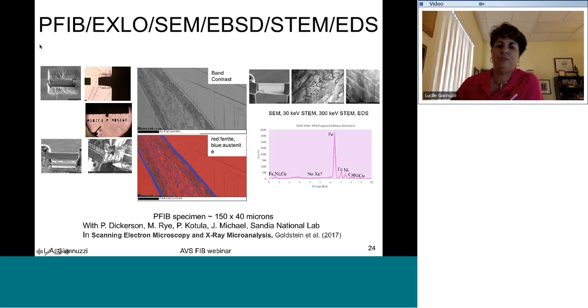The xenon, of course, gives you some added benefits. One is that because it's heavier, you get reduced sidewall damage. And two, you can just do larger things. So this is some work that I did with Joe Michael and his group at Sandia, showing lift out of a meteorite sample, put on these special grids, which I'll tell you about later. EBSD off of the surface. And this was, I think, finished with 10 kV xenon, and then back into the plasma FIB for additional thinning for STEM and EBSD work. So yeah, you can do this. This plasma FIB specimen was about 150 microns by about 40 microns, so not a problem. Okay, I'll give you some other examples.